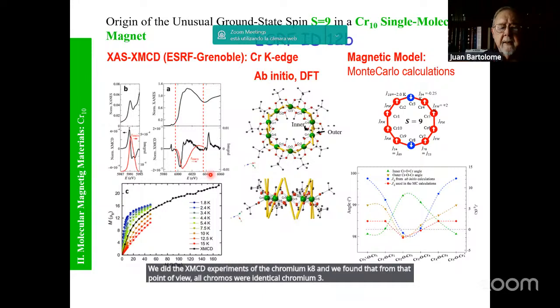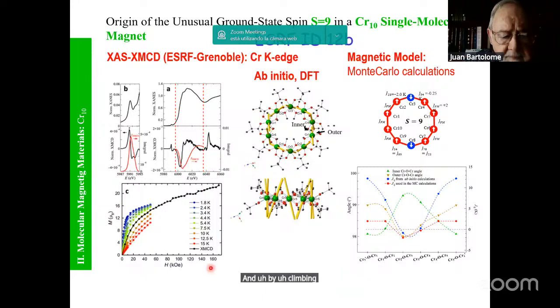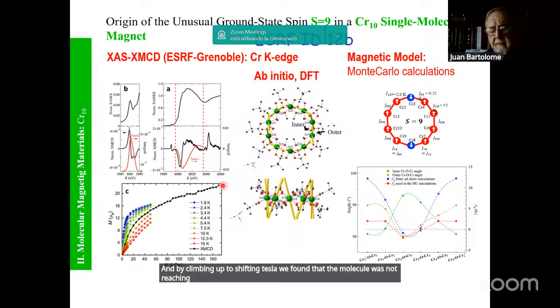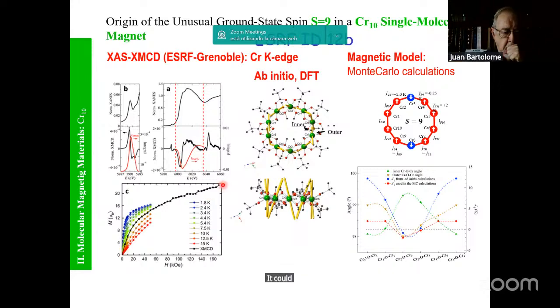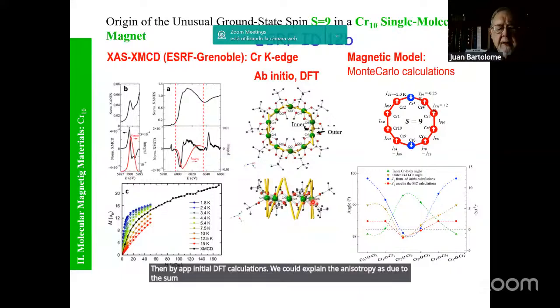And by climbing up to 16 Tesla, we found that the molecule was not reaching magnetic saturation indeed. It could go up to 25. Then by ab initio DFT calculations, we could explain the anisotropy as due to the sum of each chromium anisotropy, which were proven to have their axis nearly parallel to the vertical axis.